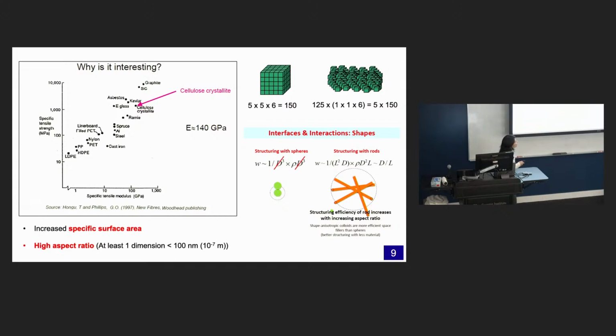That means if you're thinking about the same properties, same strengths, if you have a high aspect ratio, you need to use less material. So it's much lighter, but you can get much higher strength. If you have cellulose crystalline, you can get really high strength materials. So you can use it for airplanes and cars. So that's very good for cellulose.